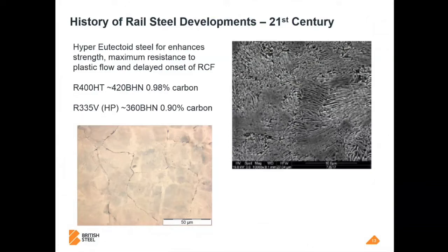So the other widely available hyper-eutectoid grade on the market has been developed by British Steel, and that's R335V is its modern new name, but it's branded high-performance or HP rail steel. This is a 0.9% carbon alloyed steel. We have quite high silicon, maybe 0.9% silicon, and we have 0.1% vanadium in there, so it's a carbon, high silicon, vanadium steel.